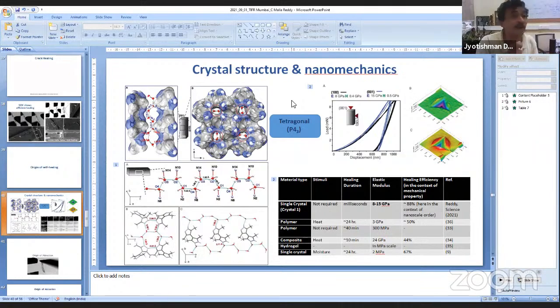But I believe it's not, because if you do this experiment where you break two needles separately, there will be 4 combinations, and you will look at 2 combinations that will work out. So if that is the case and it's just the charge, then that would create those 2 perfect crystals afterwards. However, my point would be, it is much more deeper than just that, simply because you have perfect alignment. And the perfect alignment can only appear with molecular forces at the level of directional bonding.